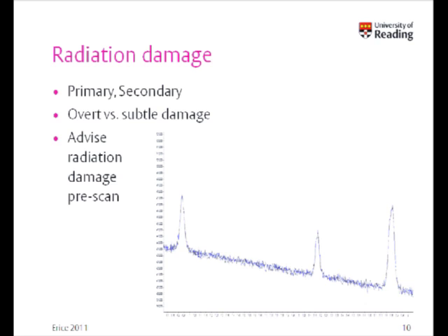In our recent trip to Diamond, the majority of samples that we looked at exhibited radiation damage in a period of less than 20 minutes. So you really have to think about the way that you set up your experiment. Gone are the days, I think, at least without some of the automation benefits that we'll see, of sticking the sample on and disappearing either to the coffee room or to the pub and coming back 8 hours later for your data set.